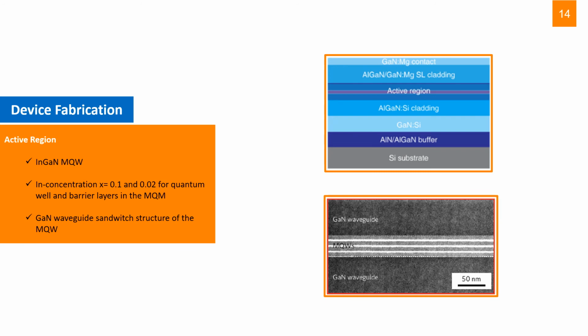The active region, as I said, is a multiple quantum well of indium gallium nitride with concentrations x equals 0.1 for the quantum well layer and x equals 0.02 for the barrier layer in the multiple quantum well. And a thick gallium nitride and aluminum gallium nitride doped with silicon are used as waveguide and cladding for better optical confinement of the device.